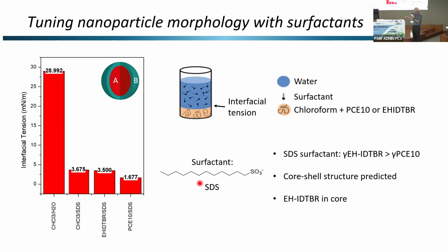But when we look at the difference here, you'll see that when you add your surfactant to your non-fullerene acceptor, we have twice the interfacial tension as we do when we have our donor polymer. So this is a lower interfacial tension. So when you just think about that, what would you expect to happen? Well, thermodynamically, you would expect the lower surface tension material to go to the surface preferentially. So we would have expected to have an EHIDTBR core with a PCE10 shell. So that's what we thought would happen on the basis of a very simple effect of interfacial tension. Of course, there are other effects due to solubility and spinodal effects that can happen as well. But on a very first pass analysis, that's what we would expect.